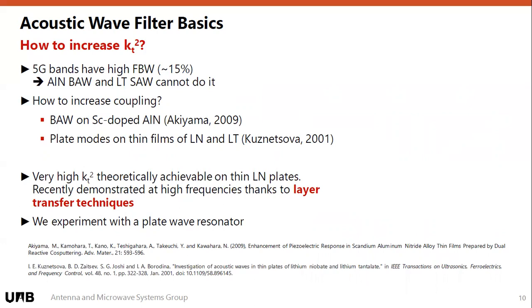Increasing viscous losses a little bit, but in the end, this is now standard in the industry. So even from really low values of doping with scandium to really high values, you can play with the coupling around. And on the other side, there's what was proposed by Kuznetsova many years ago, just from a theoretical standpoint, because this was not actually manufacturable at the time.